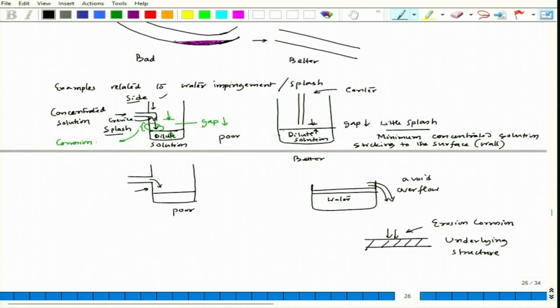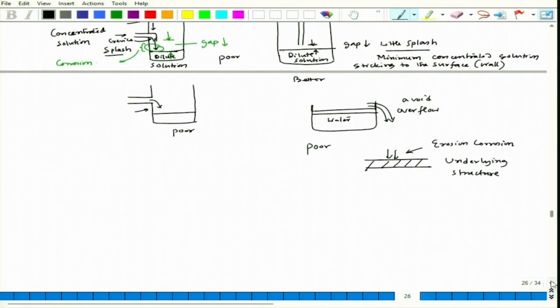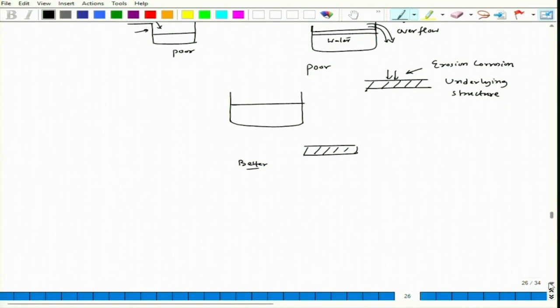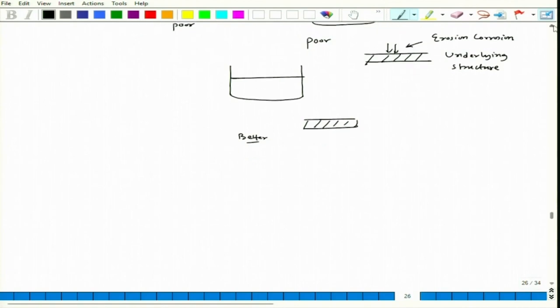It actually avoids waste of water, as well as this impingement corrosion related problem can be avoided. So, the better design would be, this is poor. So, the better design could be, we have a tank and we make sure that the water line should not go beyond the edge of that particular tank. So, overflow is stopped. So, it stops wastage of water, as well as even if that underlying structure is there, there is no question of having impingement. So, this is a better design. Fine. So, this is related to impingement or splash related problems.